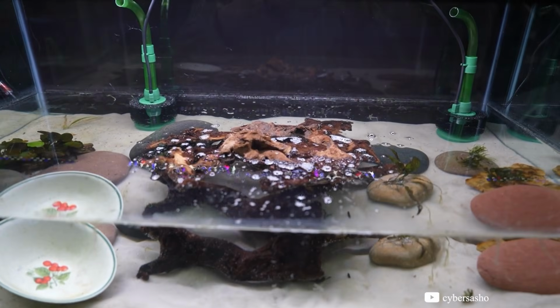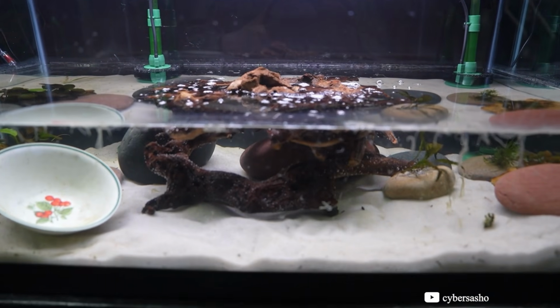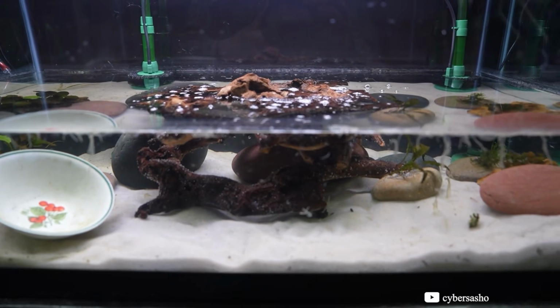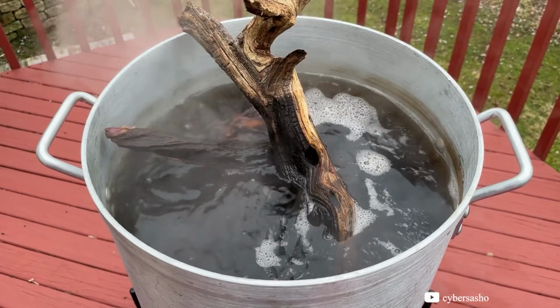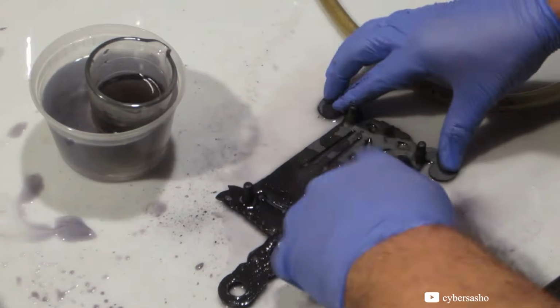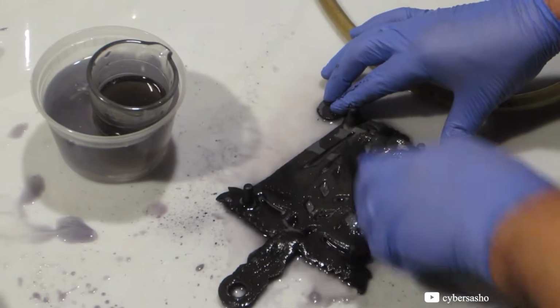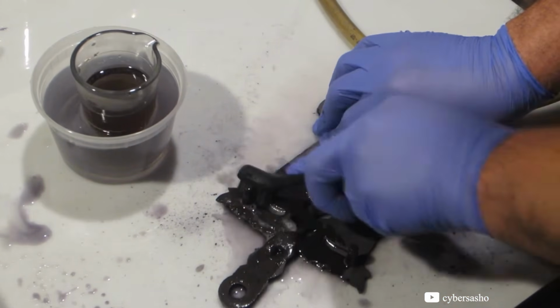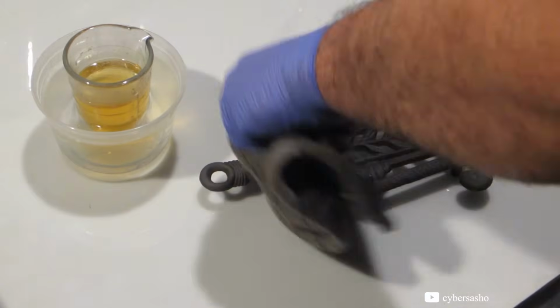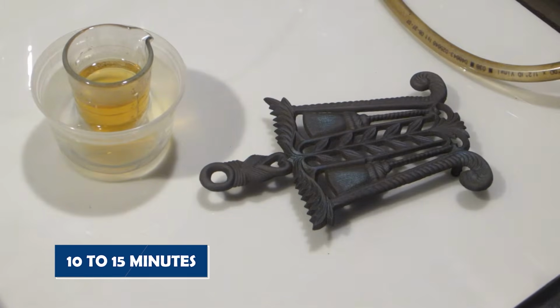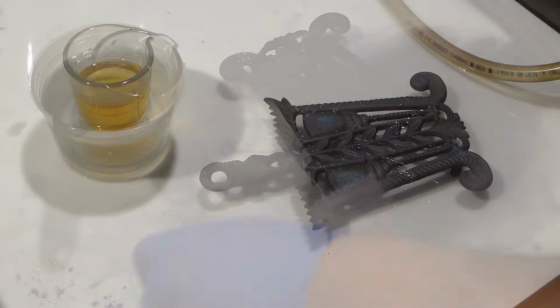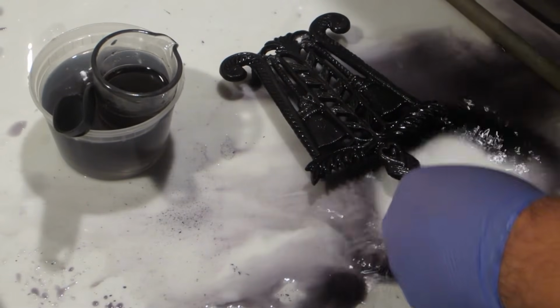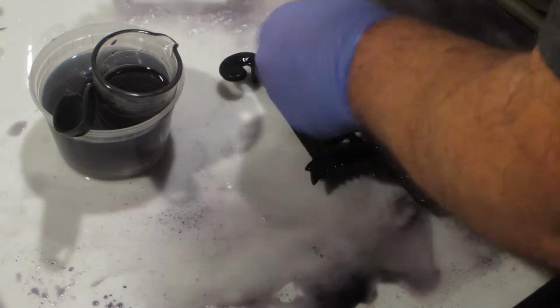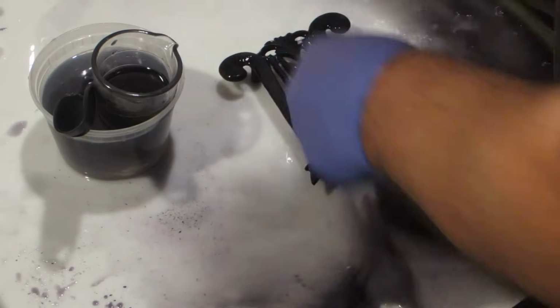Simmer them in water for about an hour, roughly a double handful of bark per liter. What you get is a dark brown liquid naturally rich in tannic acid. Let it cool, then apply it to the rusted surface with a brush or cloth. Keep it wet and reapply as it absorbs. Within 10 to 15 minutes, you will watch the color shift from orange-brown through gray toward black. That color change is iron tannate forming in real time.